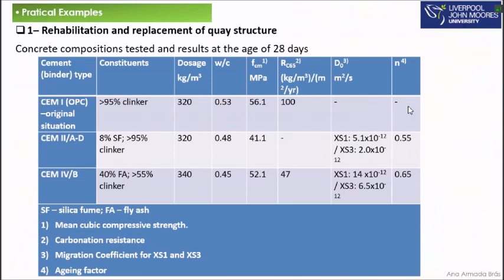So we tested the concrete with cement type 1, cement type 2, which includes 8% of silica fume, and cement type 4, including 40% of fly ash.